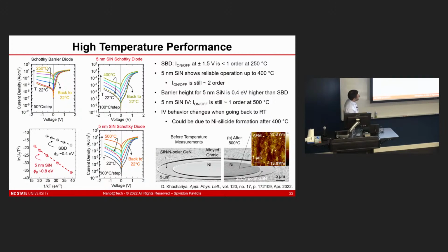It does change a little bit in its behavior, so you probably wouldn't want to do this on an everyday basis, but you can deploy these devices at hundreds of degrees and still see diode-like behavior. And when we looked at trying to understand what was going on here, we can see that there's a little bit of a change in surface morphology there. And at the temperatures that we're working with here, there is well-documented alloying between nickel and silicon. So we think that we've created some sort of silicide at the interface there. So the reaction is probably more to do with the metal to silicon nitride interface changing rather than the underlying silicon nitride to GaN interface.